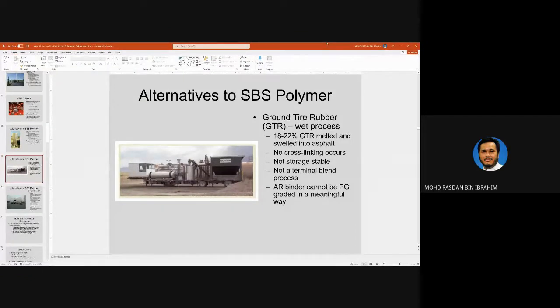Okay, using ground tire rubber, meaning that the old tires that have been used up, we can grind it up and use the rubber particles to modify our bitumen. So usually the percentage is between 18 to 22. I personally haven't used this much percentage of rubber into bitumen. The highest that I have used is 12.